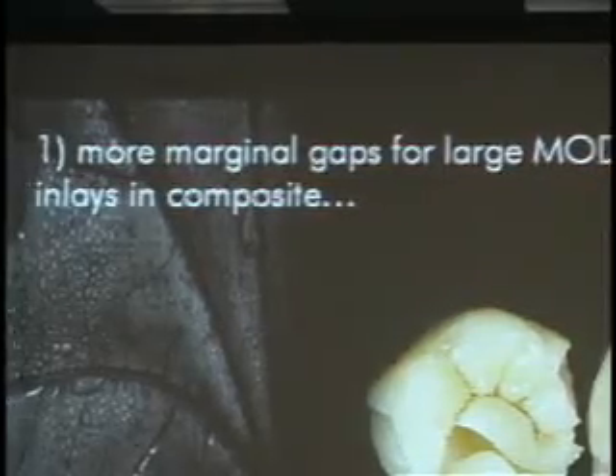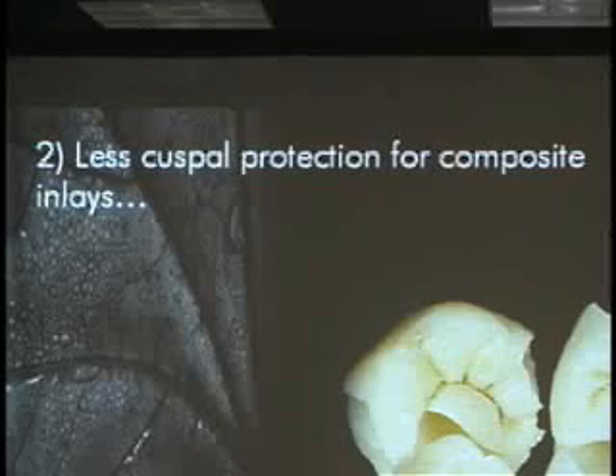This is another study, again an in vitro test, 50,000 cycles at 50 newtons, and then a load to failure. In this study, there was a trend again for more marginal defects for composites, less cuspal protection. We know that composite is not an enamel substitute, it's more a dentin substitute. Porcelain is stiffer and more enamel-like. So when we replace a large amount of enamel by composite, we can expect less tooth-like behavior, and ceramic will give you a more tooth-like behavior in terms of biomechanics.